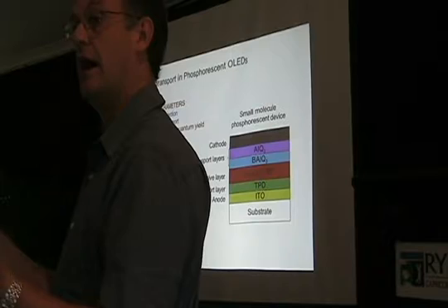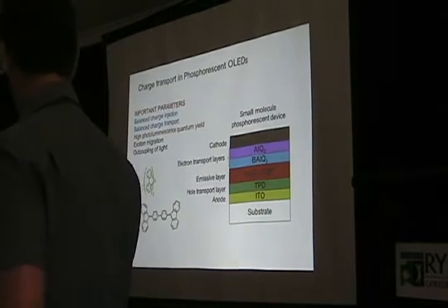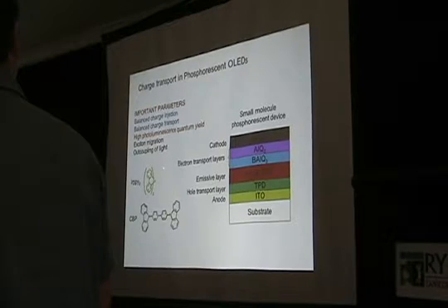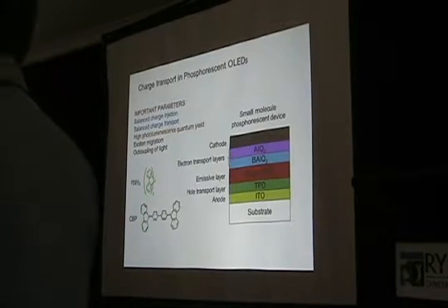So you have a tension between good charge transport and light emission, because if you bring two emissive chromophores close together, you form excited state dimers, and you end up with a redshift in your emission and a lower photoluminescence quantum yield. That's why people often blend these small molecule emissive components with a host component.